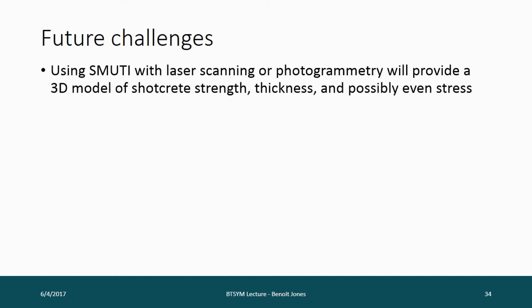And I say there, possibly even stress. If you could measure convergence accurately enough, you could calculate strains and then back calculate stresses. And if you were using it with thermal imaging, that would give you really useful information about the maturity of the shotcrete, because all the properties of concrete are correlated to degree of hydration. Age is a really poor measure of maturity. Degree of hydration is the perfect measure of maturity. So all these parameters like strength, stiffness, shrinkage parameters, creep, even coefficient of thermal expansion, are correlated to degree of hydration much better than age.